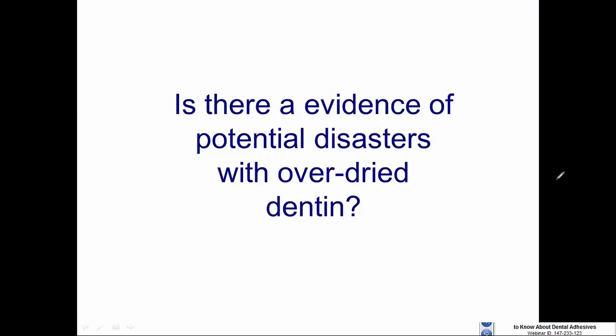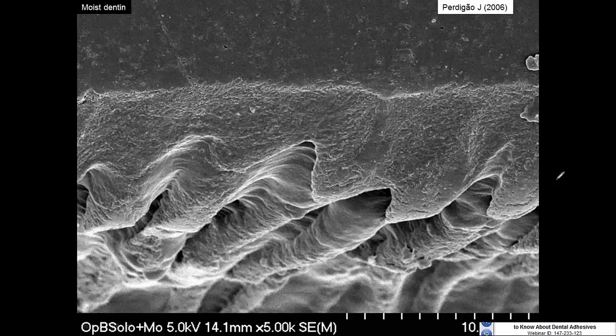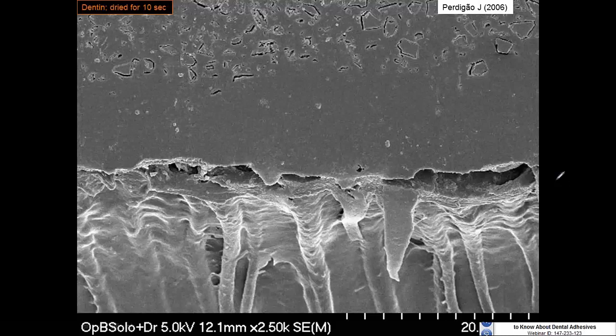Now, is there evidence that we can get disasters with overdrying dentin? This is a scanning micrograph of that hybrid layer using moist dentin from Dr. Perdigão at the University of Minnesota. Fully integrated, well-formed, very good seal hybrid layer. This is the same adhesive after the dentin has been dried for 10 seconds, showing the collagen collapse has prevented the full penetration of these resin monomers.